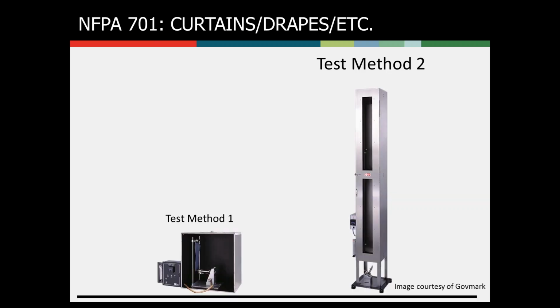The second test is test method 2, much larger scale, as you can see, than the first test method. This is for fabrics that have a weight greater than 21 ounces per square yard, and it's tested inside a cabinet that's approximately 1 foot by 1 foot by 7 feet high. And you've got specimens that are much greater too, as you can imagine. So 5 inches by 48 inches, so 4 feet high. So you're testing almost a full-scale drape or a curtain in this case.